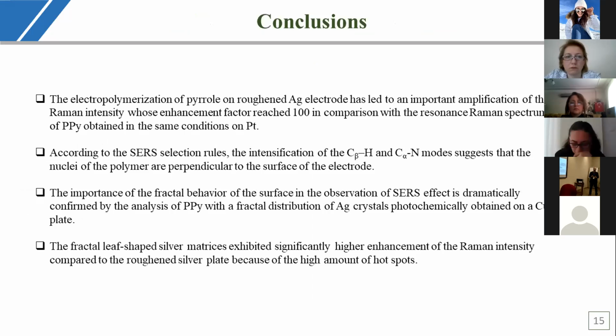As a conclusion, the electropolymerization of pyrrole on roughened silver electrode has led to an important amplification of the Raman intensity, whose enhancement factor reached 100 in comparison with the resonance Raman spectrum of polypyrrole obtained in the same condition on platinum. According to SERS selection rules, the intensification of the CH and CN modes suggests that the nuclei of the polymer are perpendicular to the surface of the electrode.